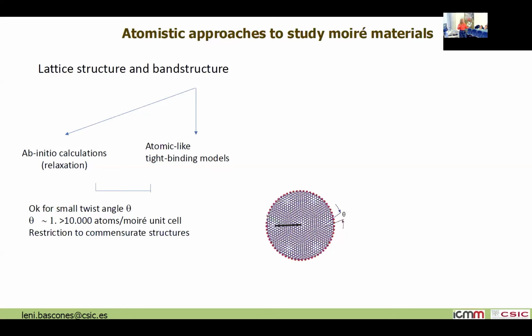So another possibility that one could think of is to say, okay, maybe if we know from having 2 layers how the tunneling between the 2 layers is going to be, one can do some type of atomic-like tight-binding model. That is to say, okay, we put all our lattice and we put the tunneling between the atoms, and try to get the structure from there. So this is somehow less consuming, and there are some people doing that. Again, in any case, your unit cell is very large. And in fact, what is really controlling your behavior is all this moiré unit cell.